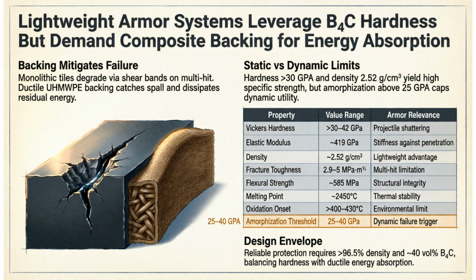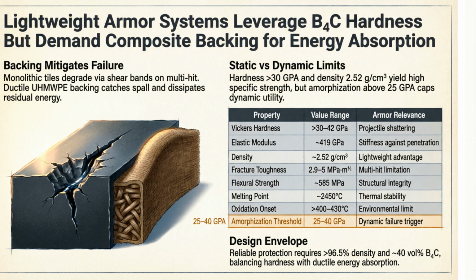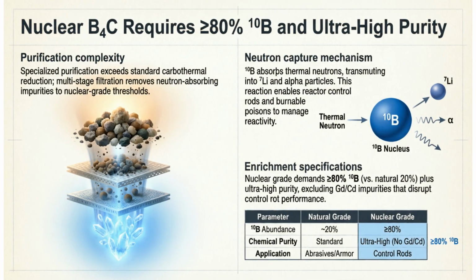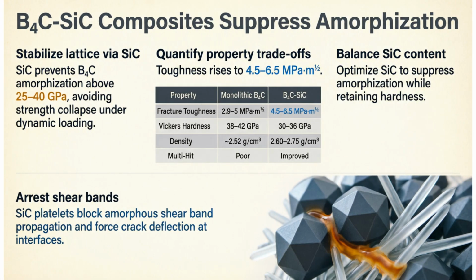To overcome these limitations, lightweight armor systems often pair boron carbide with composite backing to absorb residual energy and mitigate the effects of brittle failure. For nuclear applications, boron carbide requires specific enrichment, demanding at least 80% boron-10 and ultra-high chemical purity to function effectively in control rods. One solution to the amorphization issue is the use of boron carbide silicon carbide composites, which can suppress shear band propagation and improve multi-hit performance.